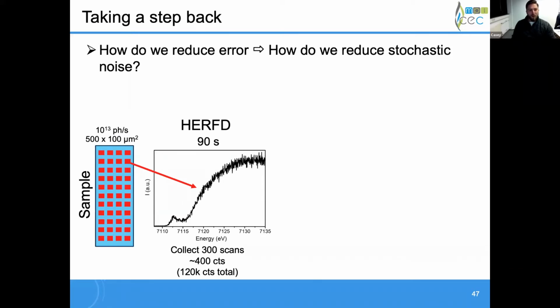And so in the HERFD experiment, as I mentioned, we have relatively short times with more intense beam, because we have to have more intense beam to get enough counts to do fluorescence measurements. And we have a relatively, not tiny, but kind of a medium spot size here. And so what we found in these samples, that we could have a scan for about 90 seconds, which is really pretty stable. But even with 300 scans, getting about 400 counts per scan, we don't have significant enough changes.